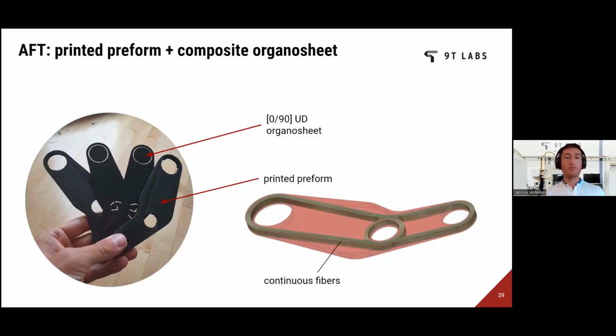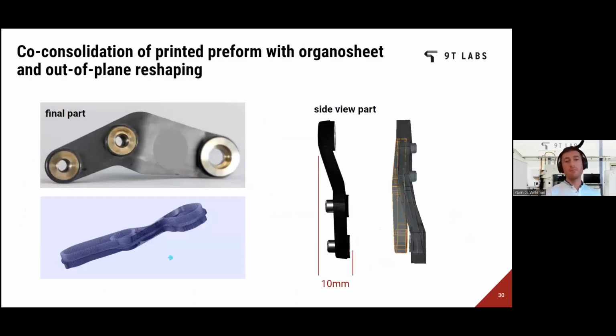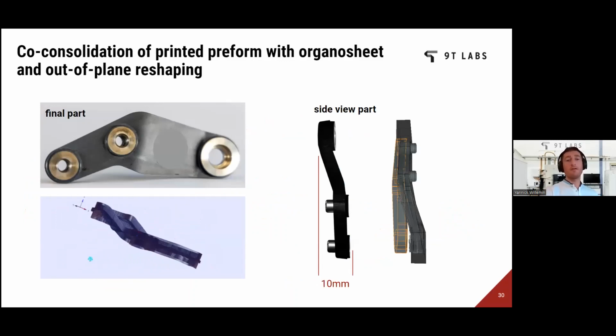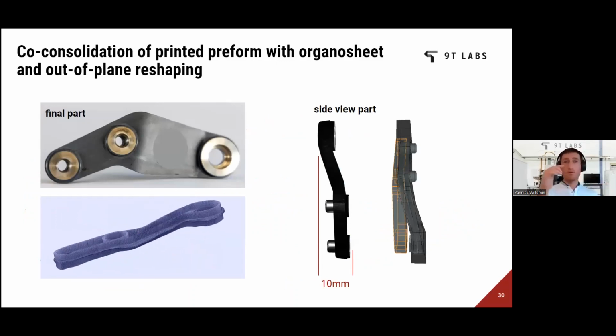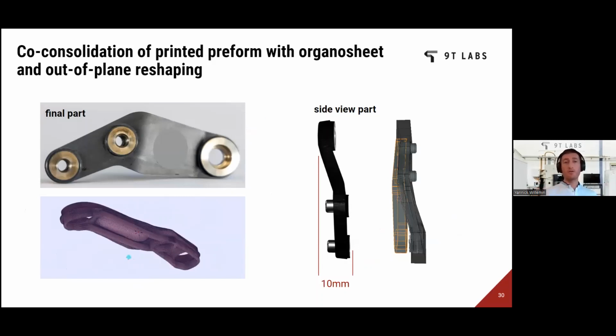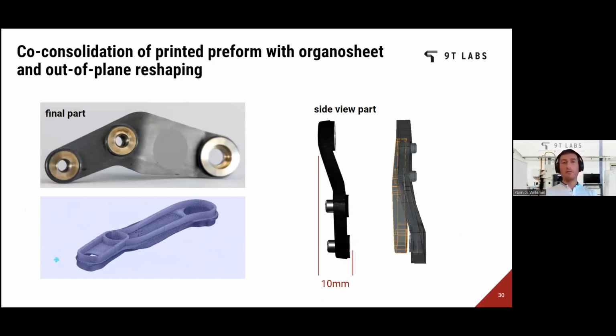We did some iterations, and we found out that we will place at certain locations of the stack those 0/90 unidirectional organosheets and combine them with printed preforms. So you see the printed preforms have already a stacked design, so they are not the same at each layer from the layer point of view, but then we even add organosheets within the final stack. So how does it look like? Basically, when we come out of the printer and also the organosheet, all those parts are 2D. They are flat, isn't it?